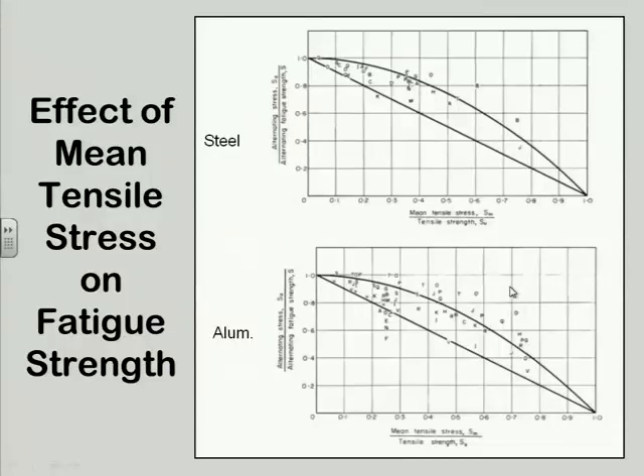But if you did a parabola fit to the data of all those tests, it would look like that Gerber line. That's considered to be the most accurate representation of the statistical parameter of this mean stress versus alternating stress. But notice that there's an awful lot of parts breaking below that parabola. And we want to take a line of that sort as a limit to determine our safety factors. So it's generally believed or felt by engineers that the Gerber line is the best to use when you're trying to analyze forensically a fractured part, because it's going to give you accurate data. But it's not a very good line to use for design on the front end. So most engineers will use the Goodman line instead. And I'll show you these lines again along with a third one in an upcoming slide.